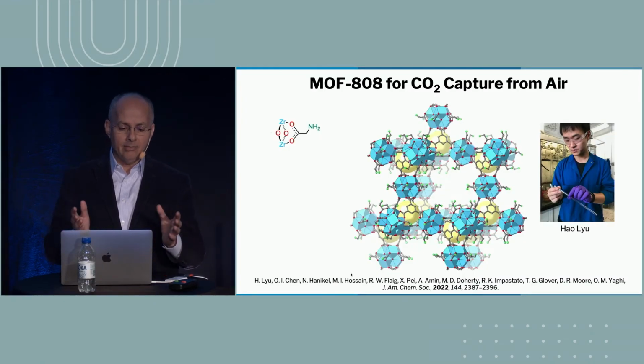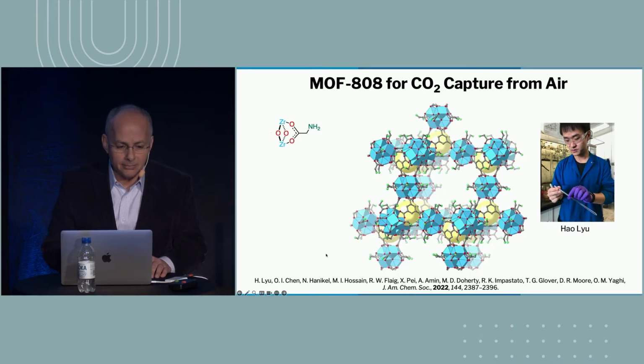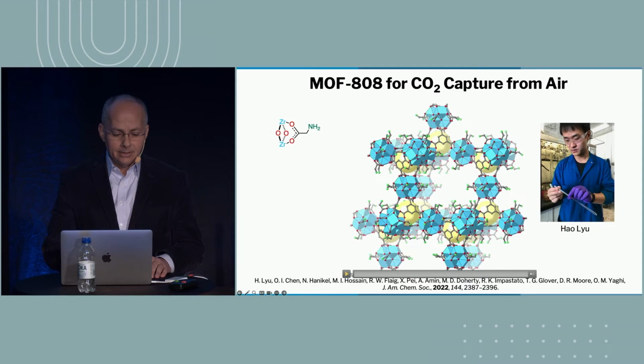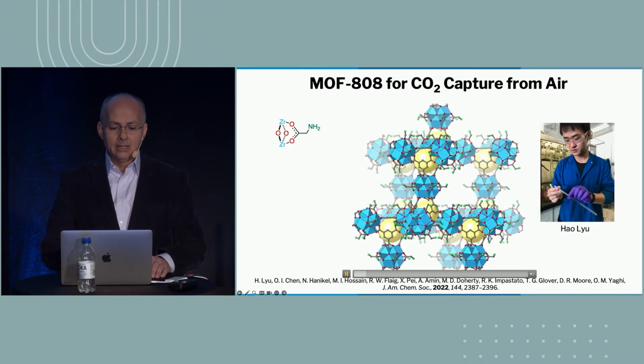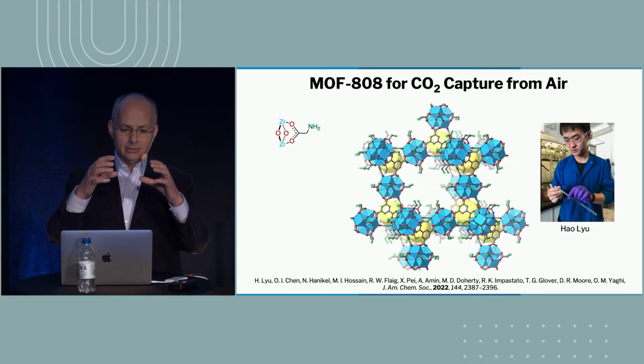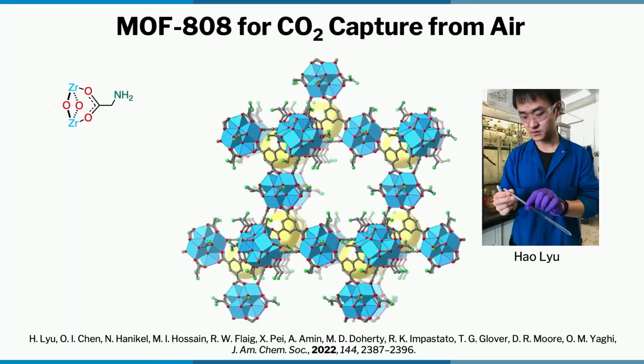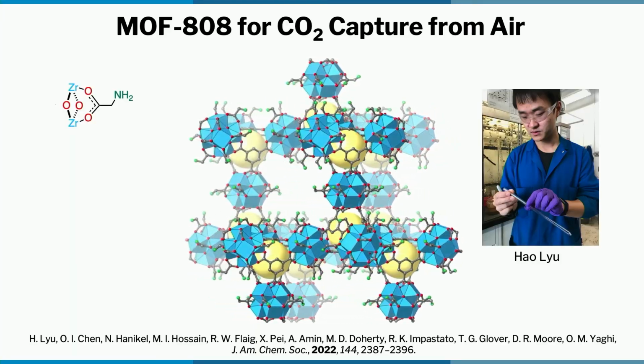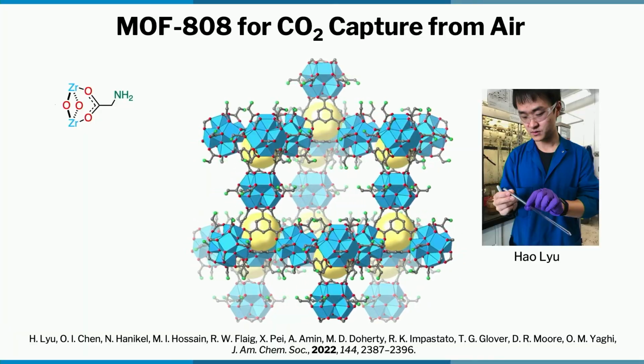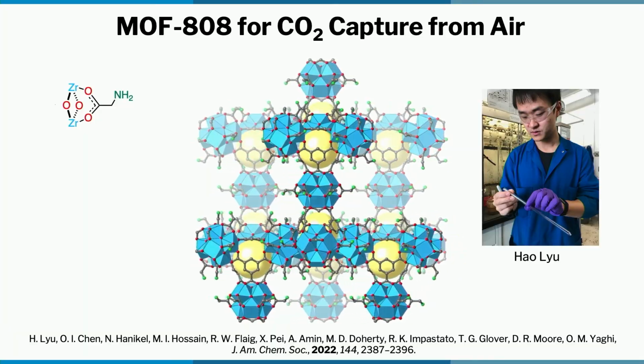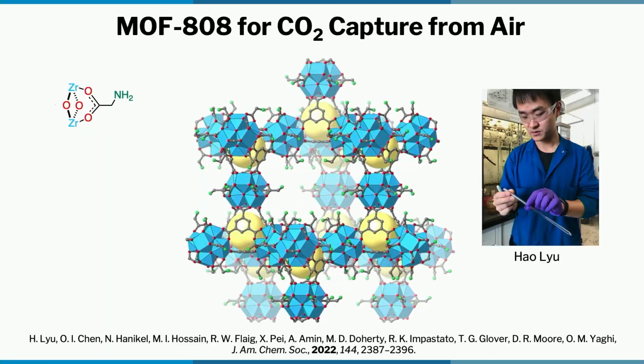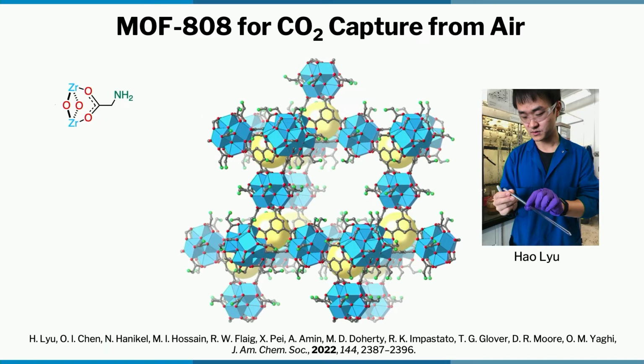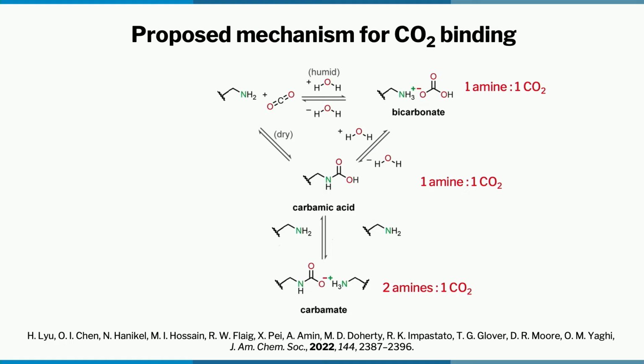So here's how this chemistry works. Here's a MOF, and we call it MOF-808. Let me see if I can play this. Yeah. MOF-808 is made from zirconium oxide units that are linked by trimesic acid, and you see these amine units, the NH2 units, sticking into the pores, and the pores are replete with these. And these NH2 units attract CO2 from air. Without them, you can't bind CO2 from air. Okay, so we study what CO2 is doing in the pores using solid-state NMR.